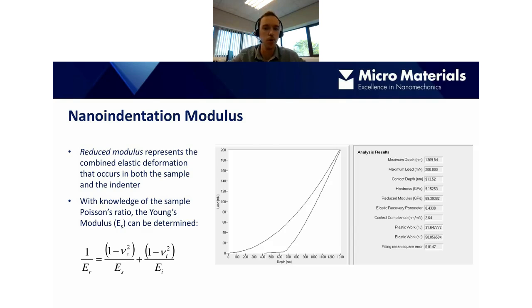In the majority of cases, the indenter material will be diamond. So we just need to know the elastic modulus of diamond and the Poisson's ratio of diamond, which are well known. All we need to plug in is the Poisson's ratio of the sample. In some cases that may be known, in others it may need to be more of an estimate. From this we can work out the elastic modulus from the reduced modulus, and the Nanotest software that we provide has a calculator to convert that for you. In most cases, for low modulus materials, there won't be much difference between the reduced modulus and the elastic modulus.